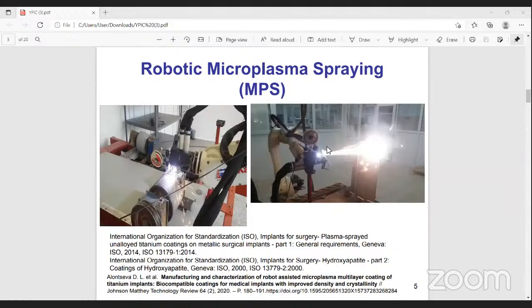The use of robotic microplasma spraying allows for precision coating deposition on complex shaped implant parts, such as parts of elbow and hip replacements. In our previous papers, it was shown that robotic microplasma spraying can produce coatings on medical implants made of biocompatible titanium and hydroxyapatite materials with a desired porosity and roughness, meeting the requirements of international standards for implants for surgery in terms of coating adhesive strength, crystallinity, and purity.